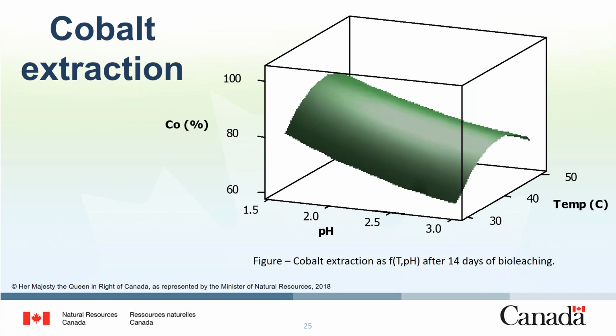Here we have the cobalt extraction as a function of temperature and pH. Cobalt extraction essentially mirrored nickel extraction, although with slightly lower extractions at the higher pH levels. And it's expected that cobalt and nickel would follow each other because they report to the same mineral, and they also have very similar metallurgy.